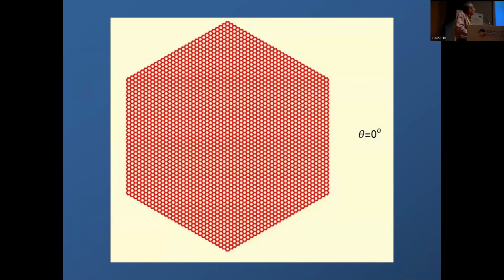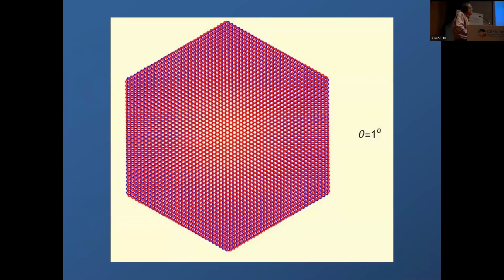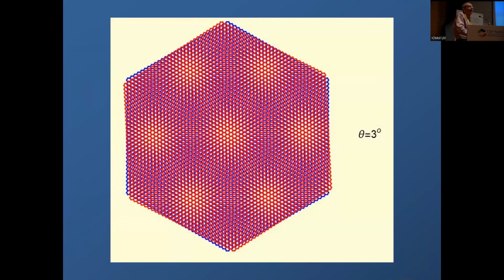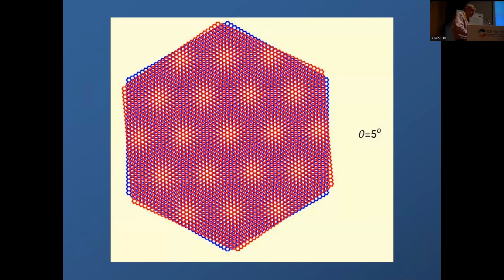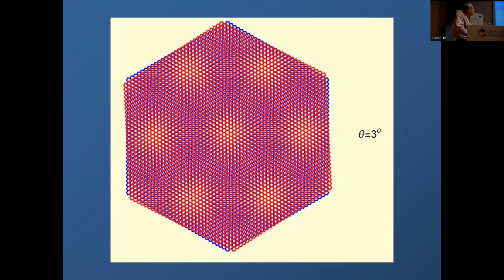This is what happens when you rotate one graphene layer with respect to the other. So you see that there are patterns like the patterns you have when you rotate graphene with respect to boron nitride. The only difference is that there is no limit to the possible lattice constant of this moire. Here you can have moires much larger than the ones you can achieve in the case of graphene, because when you put graphene on top of boron nitride, you cannot avoid this mismatch between the two lattice constants, the 2% mismatch. Here there's no mismatch, so you can make moire patterns as large as you can get.